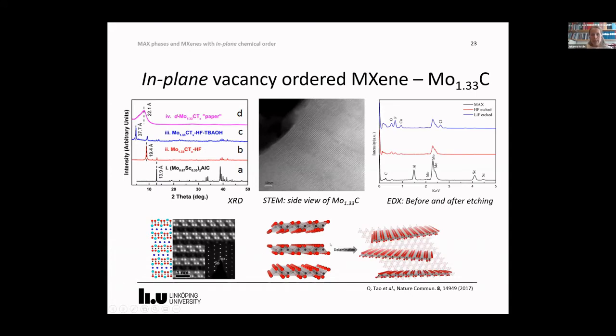And if we delaminate this multilayer MXene, filter it to form a film, and then make EDX, we can see that we remove aluminium and scandium from the MAX phase if we etch in HF or in lithium fluoride plus HCl. So both ways work.